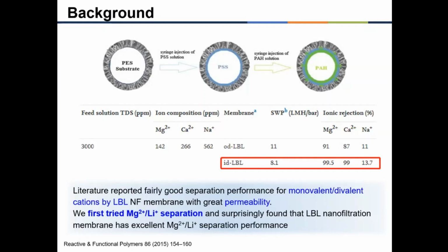Literature reports fairly good separation performance for monovalent and divalent cations by LBL nanofiltration membranes with great permeability. We first tried magnesium-lithium separation and surprisingly found that LBL nanofiltration membrane has excellent magnesium-lithium separation performance.